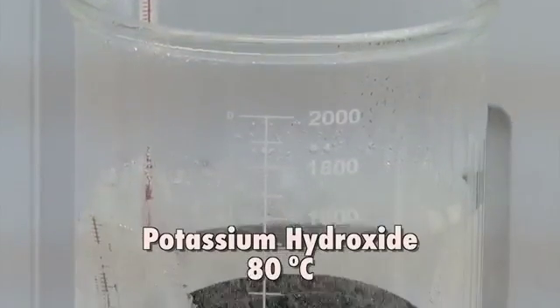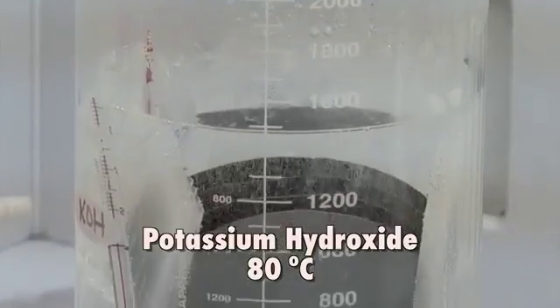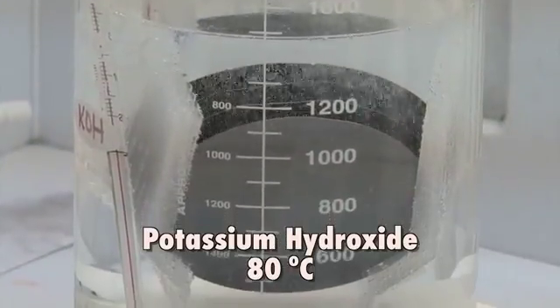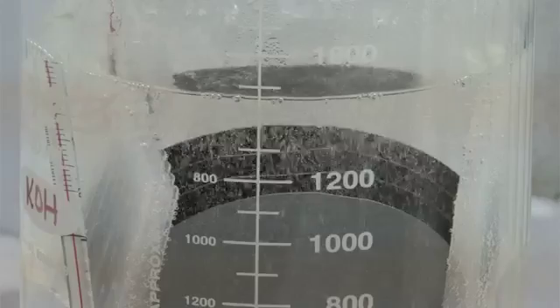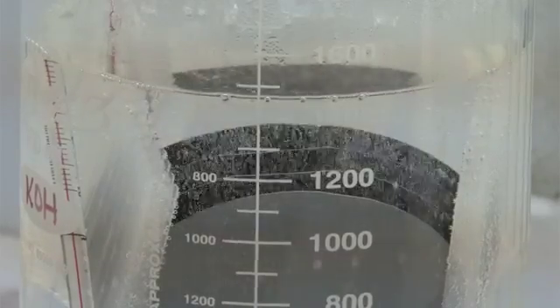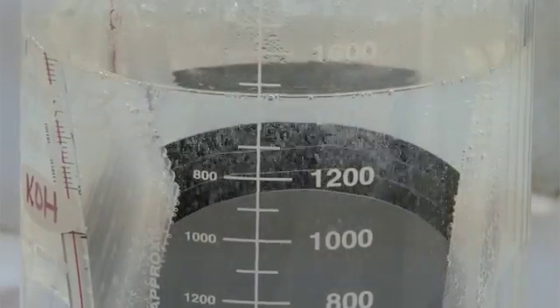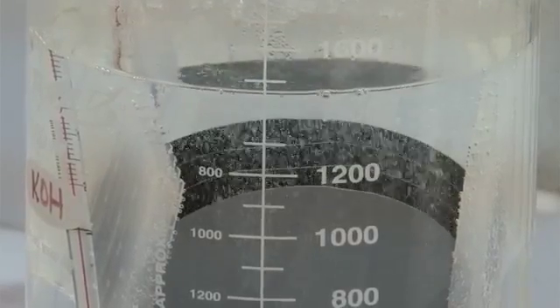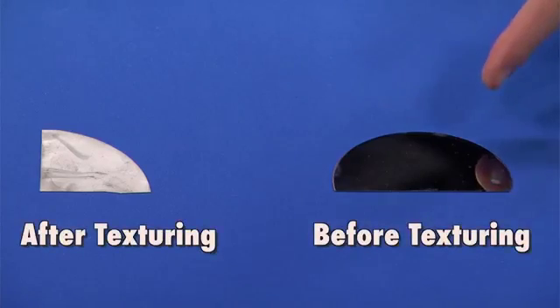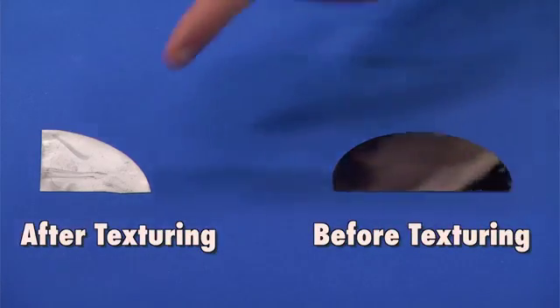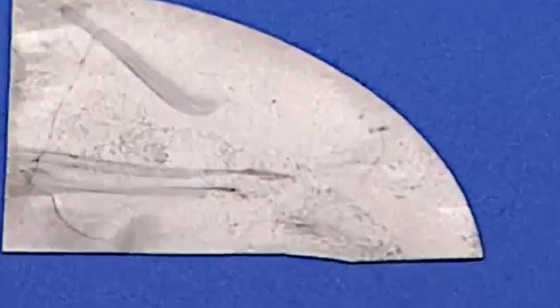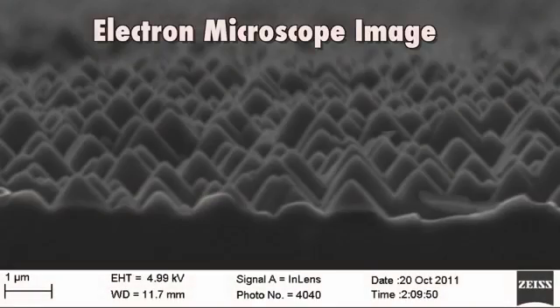In this example, we use a solution of potassium hydroxide, or KOH, which is heated to around 80 degrees Celsius. This violent reaction is actually etching the silicon and carving out little tiny pyramids on the surface. And the result is a wafer that loses its shiny appearance and appears to have a dull finish. The textured wafer is left with a surface that is covered with microscopic pyramids, whose base is around a micron, or about 1/50th of the width of a human hair. It turns out that this wafer only reflects about a third as much light as it previously did.